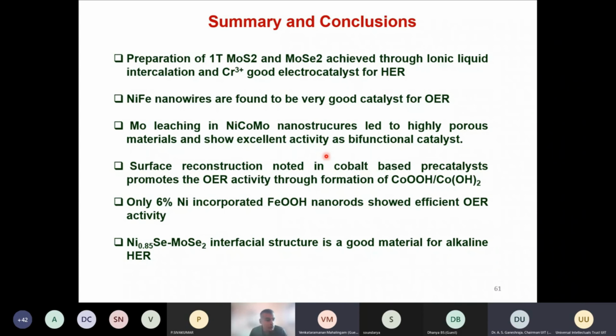We have done other samples like silicates also, but I couldn't show the results. And then we observed how iron-rich nanorods, with a very small amount of nickel incorporation, show better activity compared to the nickel-rich materials. And then we finally have shown one example of an interfacial structure formed between nickel selenide and molybdenum selenide for the alkaline hydrogen evolution reaction.